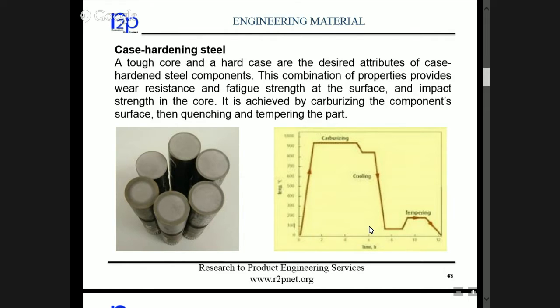Carbides are formed with the different alloying elements that are there. Since the carbon has been picked up only in the outer structure, the hardness increase will happen there only. In the inner core, the carbon was not increased, so the core will remain soft. So the component will have an outer hardened case and a soft core. For all wear applications or contact stresses, the outer harder case can take the loading and will not wear, and the life will be more. But for situations where impact is there, the inner soft core can show the ductility or toughness it retains, so that the part does not fail in bending. So by this process, we have taken care of bending failure, which may happen due to impact, and also wear or contact stress related failure, as we have hardened these.